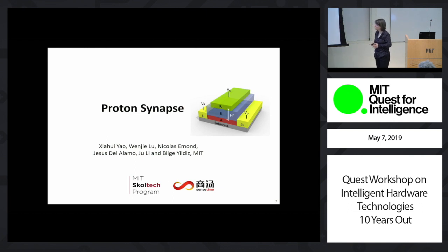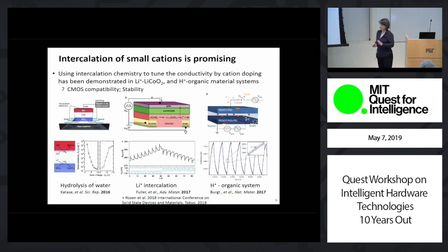And in this work, I collaborate with Ju Li, together with our joint postdoc, Xiahui Yao, on the materials and macroscale devices, and also with Jesus del Alamo and his postdoc Wenjie Lu in scaling down these devices and electrical characterization. Okay? So, small cation intercalation neuromorphic behavior. This has been demonstrated in the literature in the past few years and has taken quite a bit of attention, including our group. And here is one such work where proton intercalation into tungsten oxide is accomplished, but nevertheless by using hydrolysis of water, which requires a lot of energy, and you also don't want to work with water in a solid state device. So it's interesting behavior, but not quite feasible.